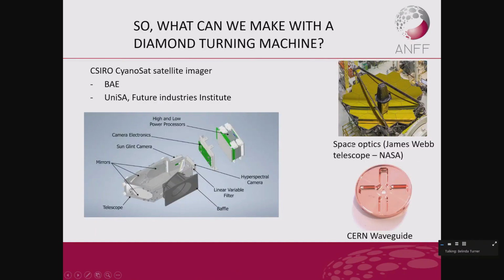So Brendan, who's here, he actually made the lenses for this satellite that went up when he was at BAE, and Colin Hall put the thin film coatings on for it. This opens up other opportunities. So a lot of these mirrors and lenses, they've got thin film coating. They've been machined with a diamond. Some of them are glass optics, which will be polished. You've got things like CERN waveguides, which need to be machined with a diamond at a certain temperature, and need to be measured at that temperature because they take into account the thermal expansion. So all the dimensions on that will be within a micron because they might put 20,000 of those together. So if they're all at the top of the tolerance, the whole assembly will be 20 millimeters longer at the end. So some of these specify you have to machine with that.